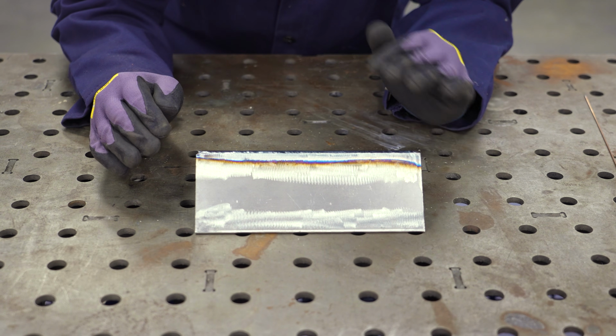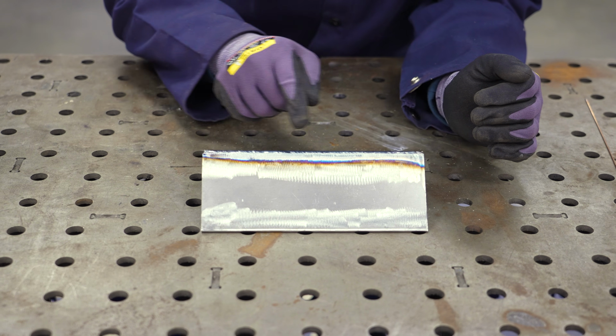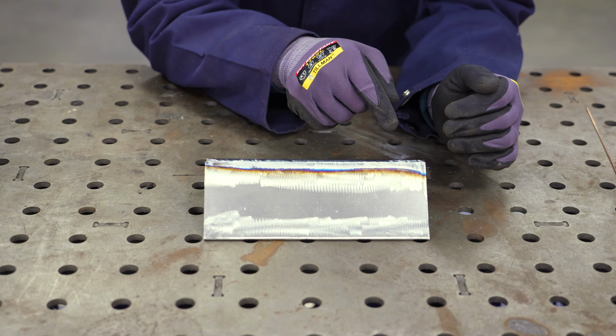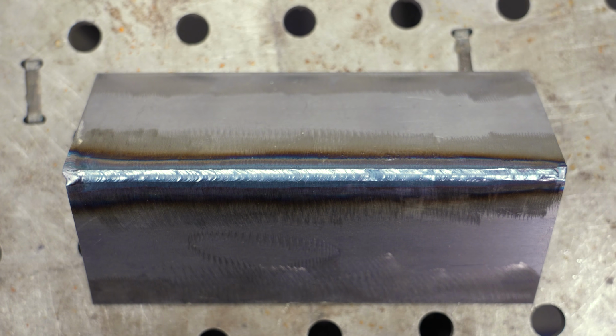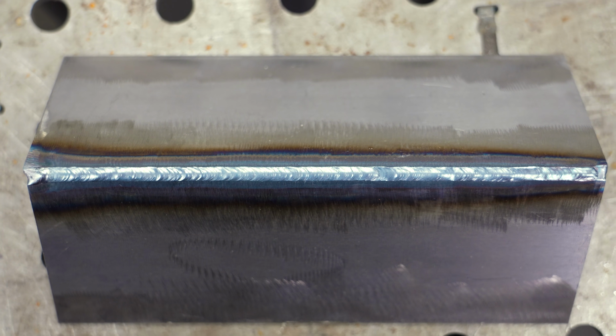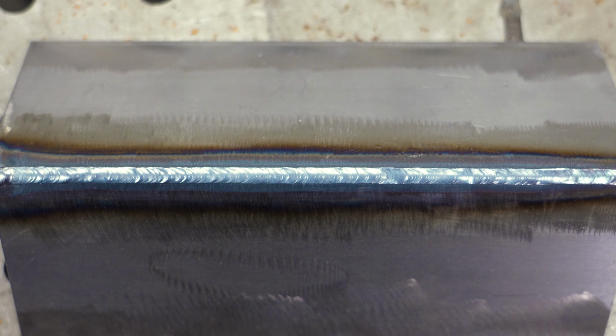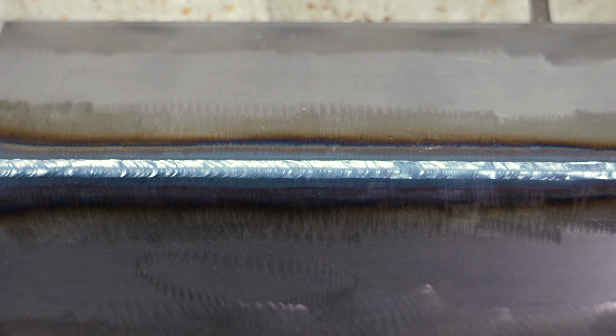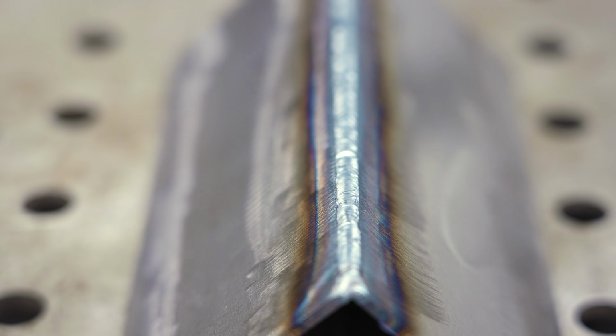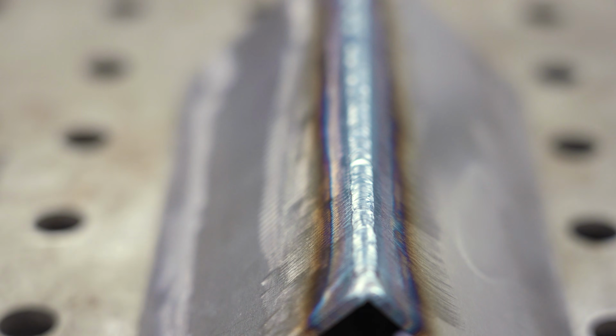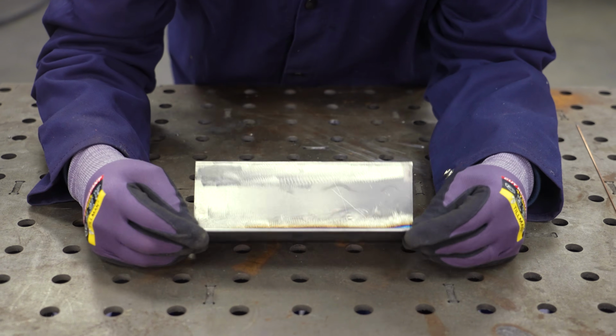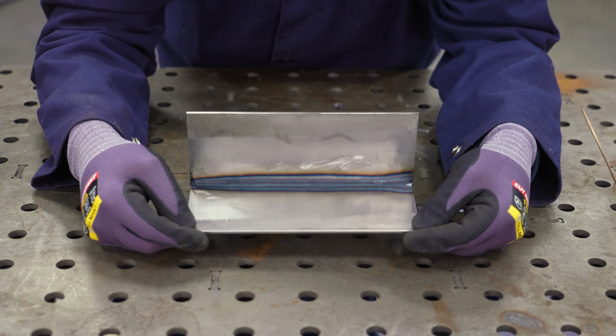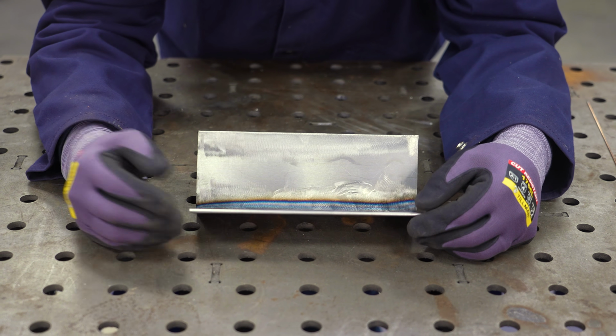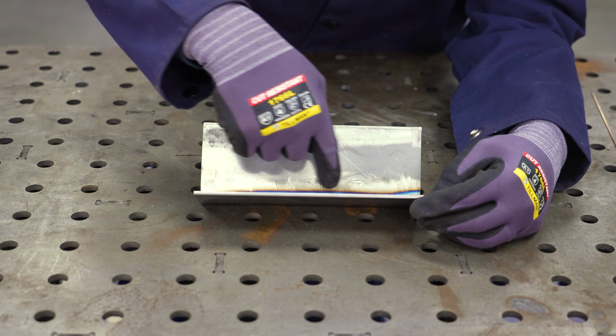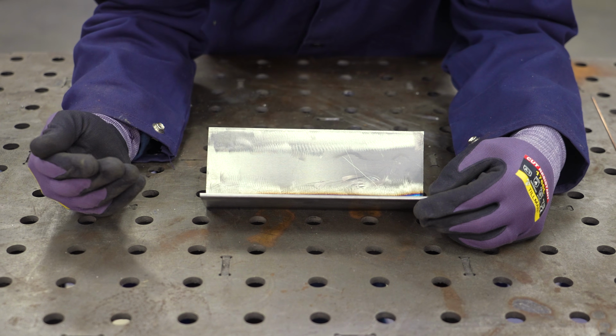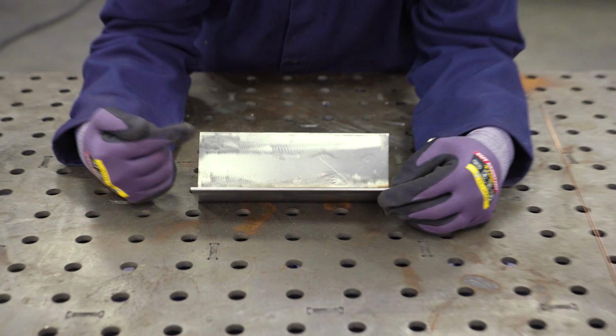So unlike the slow pulse, this went significantly quicker. I'd say it was like three times faster to weld this. You'll notice the surface is way different than the previous piece. It's a lot smoother. We don't have those dimes that you typically associate with TIG welders. And also the heat affected zone is much smaller. And like before, I don't have complete penetration, which I did not expect to have given how thick this piece is. I would again weld the inside from the backside for a functional part that has a 90-degree butt weld like this.